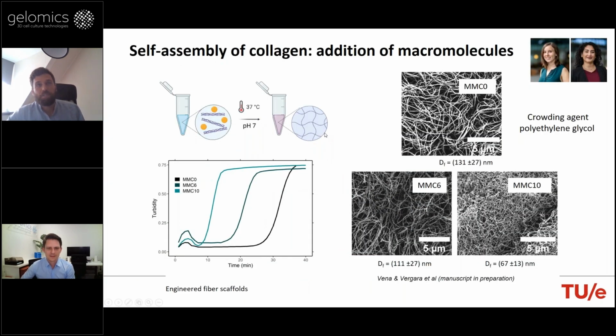Yeah, so basically what we know is that fibrillogenesis takes place in the ECM environment in the presence of other macromolecules, and some of them participate in this crowding effect. It's basically just by occupying space and then further confining the polymer molecules. And then occupying space and excluding water leads to a further confinement of the, in this case, collagen molecules, and that speeds up the process by which you move from collagen molecules up to fibrils and then fiber bundles.